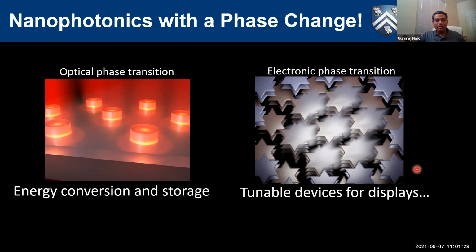And recently, I think there's also been a Science paper where they did ultrafast TEM studies on this material, and then showed that if you just hit with a pulse of laser, an ultrafast, intense pulse, then at the moment the temperature increases so much that you have heating, and the material goes through a phase transition, from nearly commensurate to incommensurate phase, and then eventually as it cools, it nucleates new domains and then goes back to nearly commensurate phase. So that will also bring in tunability.